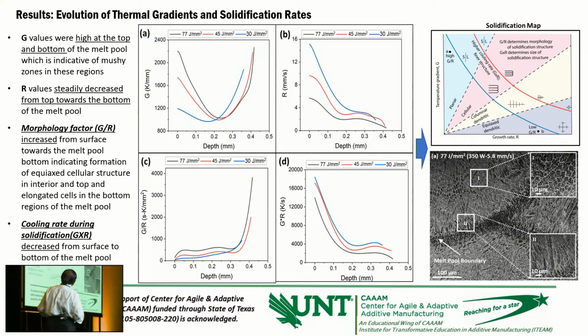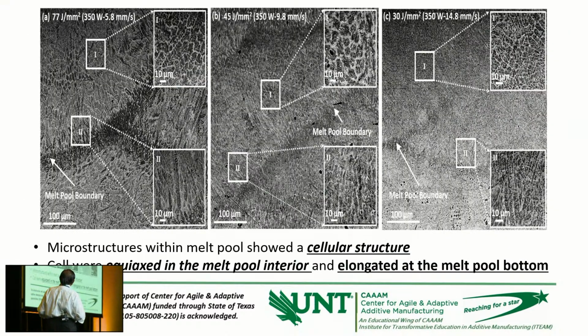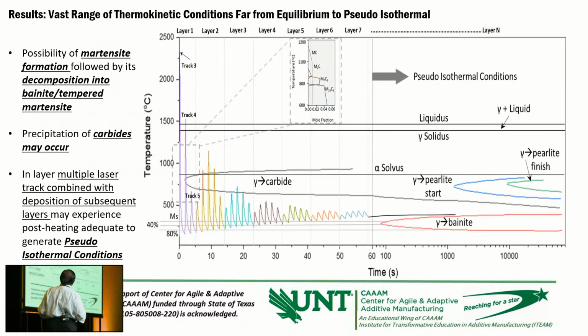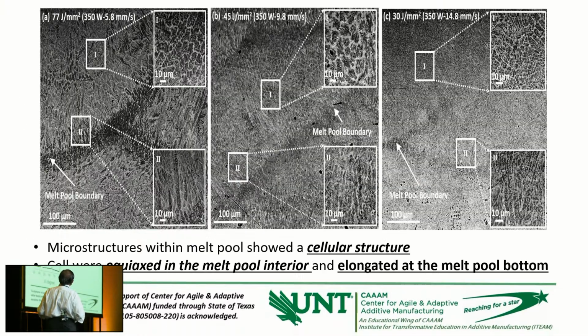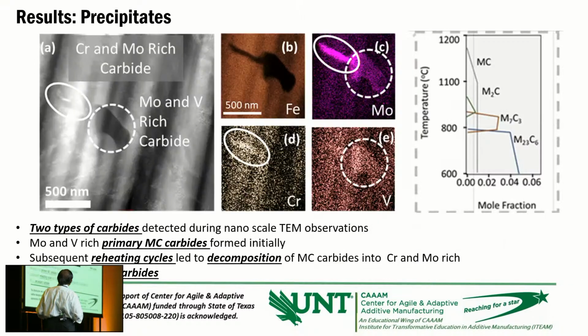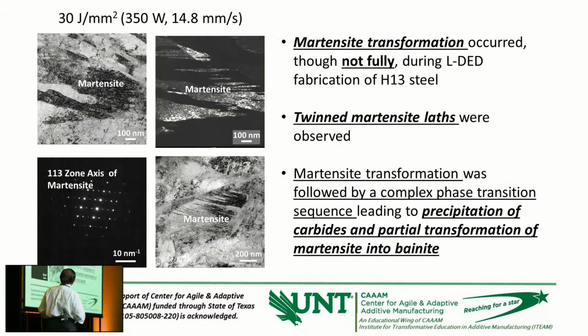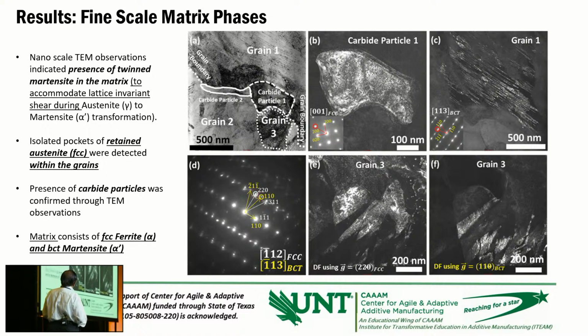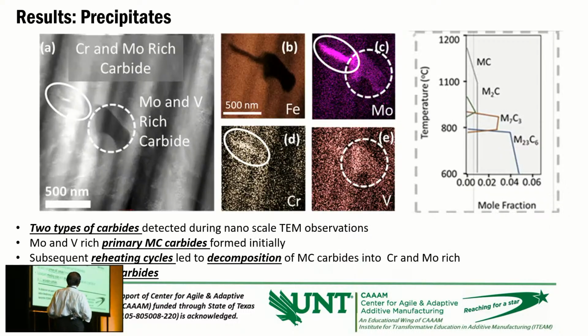You get very high cooling rates here, and those cooling rates produce this kind of microstructure where you get twin martensites and so on. Also, such high cooling rates retain austenite. The martensite transformation is not complete.